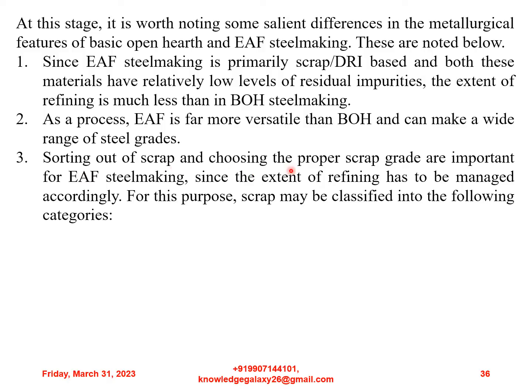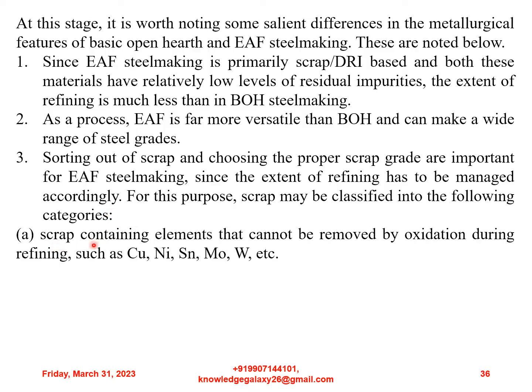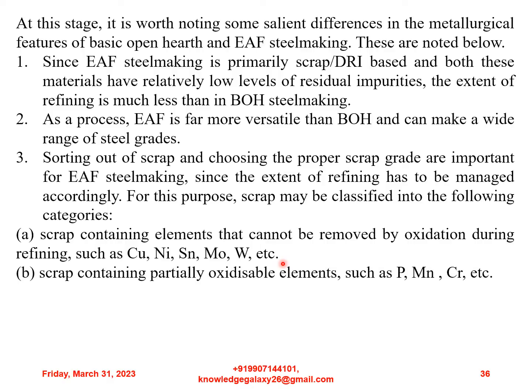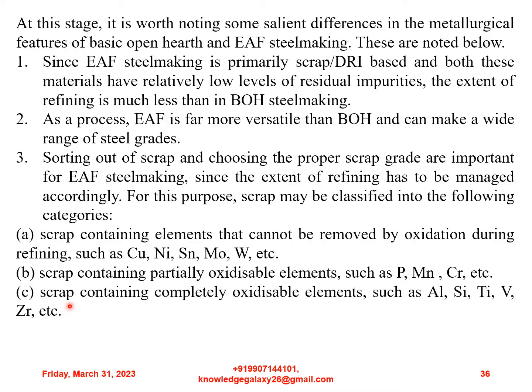Sorting out of scrap and choosing the proper scrap grade are important for electric arc furnace steel making. This is the heart of the steel making operation via electric arc furnace since the extent of refining has to be managed accordingly. For this purpose, scrap may be classified into the following categories. First is scrap containing elements that cannot be removed by oxidation during refining, such as copper, nickel, stannum, molybdenum, tungsten, etc. Next category is scrap containing partially oxidizable elements such as phosphorus, manganese, chromium, etc. Next category is scrap containing completely oxidizable elements such as aluminium, silicon, titanium, vanadium, zirconium, etc.